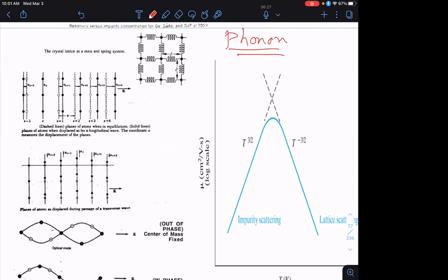We discussed that in chapter 1 and beginning of chapter 3, where remember we plotted the potential in a crystal as a function of separation between the atoms, and very far away you get the atomic levels, and then it goes down because of the bonding, and then it goes up because of the nuclear repulsion. And we said that the atoms settle at a lattice constant corresponding to the potential minimum. Now near the minimum, it's kind of like a parabolic potential, and motion of a particle in a parabolic potential is simple harmonic oscillation. Hopefully you remember that from your freshman physics class. So these springs are basically modeling the simple harmonic vibrations about the equilibrium lattice constant.